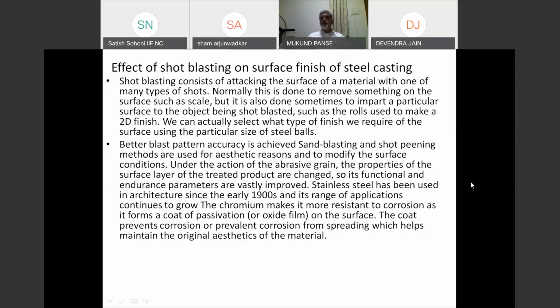But what happens is, whenever you grind these portions of riser, pads or upgradation, the natural texture of the sand casting gets disturbed, which many people object to when they are specifically looking for aesthetic appeal. To some extent, not 100%, it can be restored by excessive shot blasting of these surfaces. You have to use specific hard balls of bigger size and shot blast this casting, so some amount of natural texturing is restored.